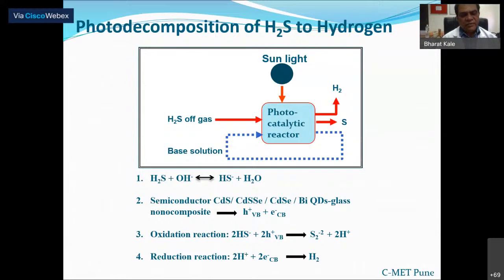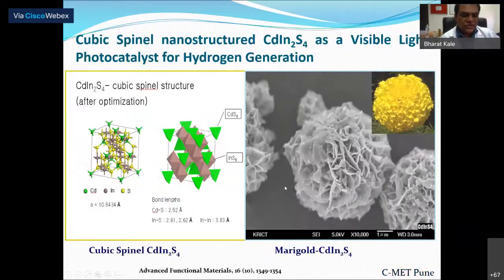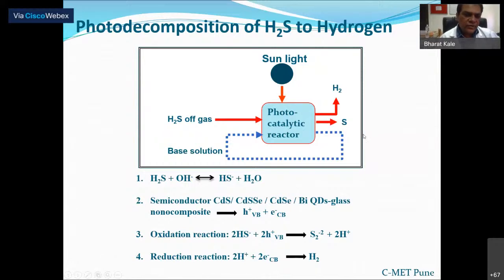During photoexcitation, electrons and holes are generated, and these electrons and holes are responsible for reduction and oxidation. Then we are making a strategy for how more sunlight can be absorbed and more electron-hole pairs can be generated. For reduction we need the electrons, and for oxidation we need a hole. So we just need to trap holes when we want the reduction, and we don't want oxidation. Electrons have to be trapped. So this combination has to be worked out during the process.